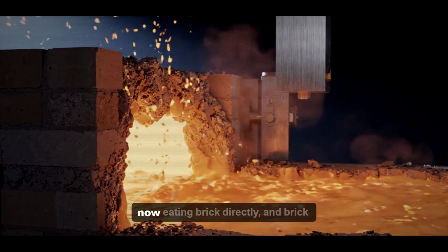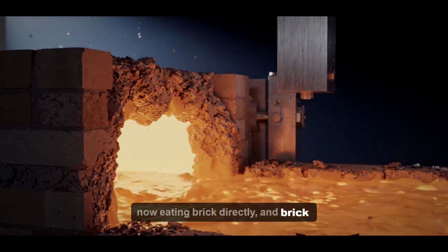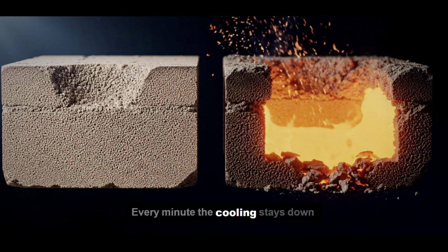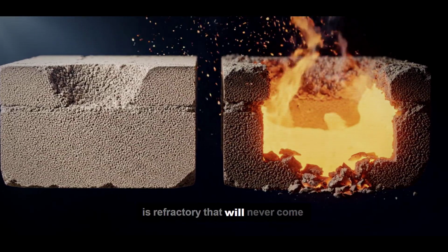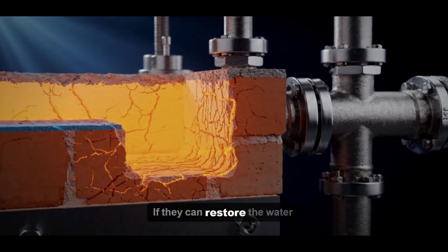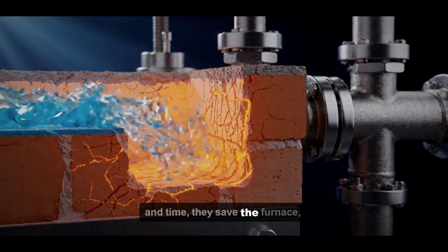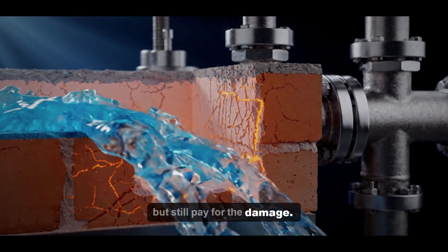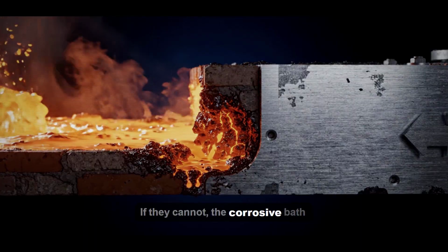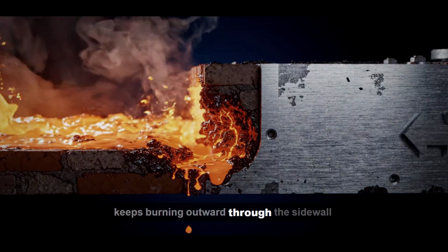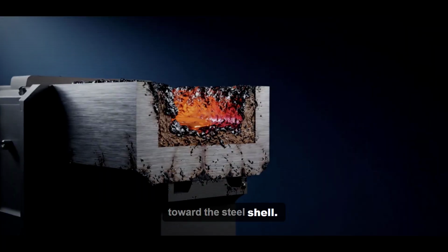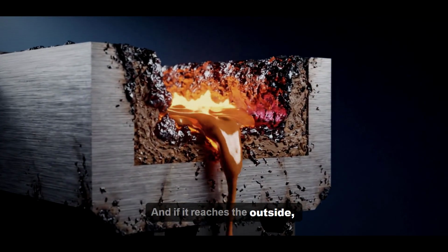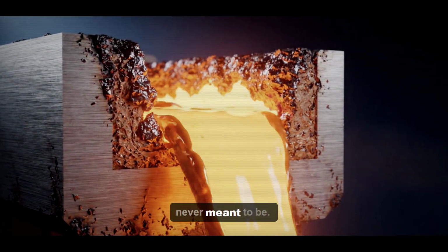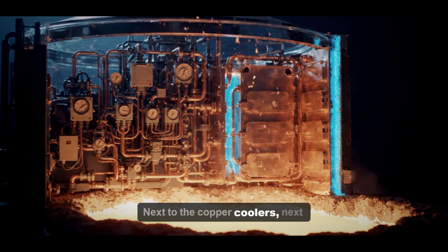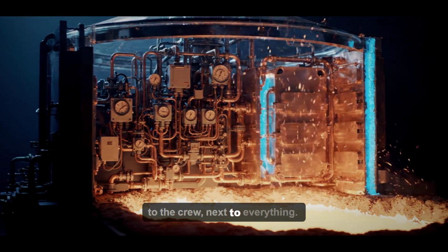The bath is now eating brick directly, and brick is finite. Every minute the cooling stays down is refractory that will never come back. If they can restore the water in time, they save the furnace, but still pay for the damage. If they cannot, the corrosive bath keeps burning outward through the sidewall toward the steel shell. And if it reaches the outside, 1,400 or 1,500 degrees of molten metal is now somewhere it was never meant to be. Next to the copper coolers, next to the crew, next to everything.